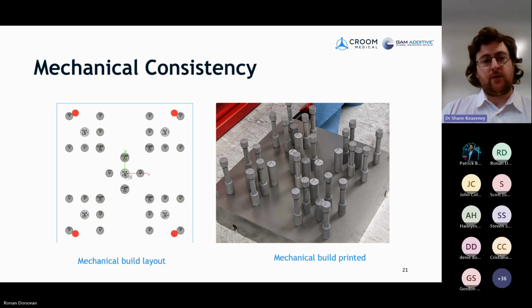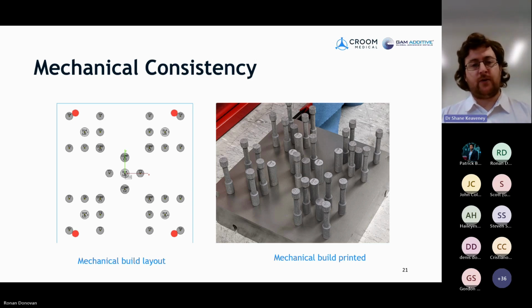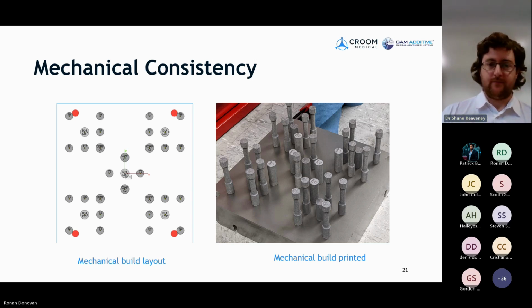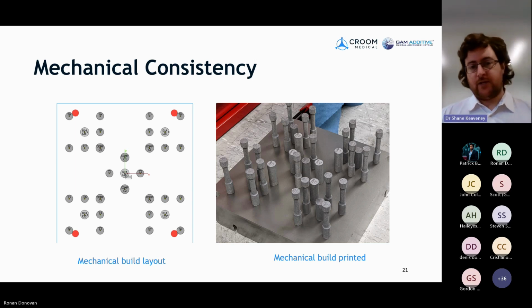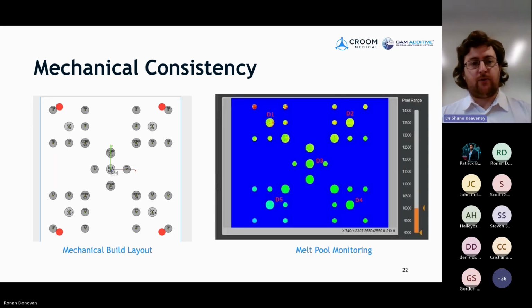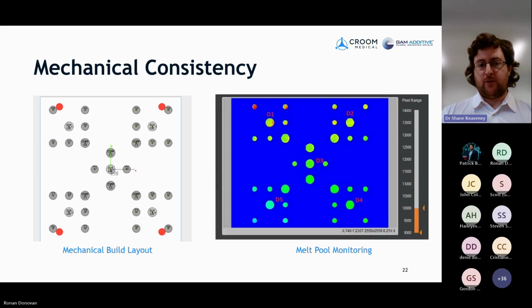Now within this, we've done compression testing, density testing, and tensile testing. And you'll see the layout here from above, and we have our printed samples here. Visually it looks quite consistent. But if we look also at the melt pool monitoring, which we have on the M2 system, which does melt pool emission monitoring as well as melt pool size, we can see we have quite a consistent color map here. So looks quite good.